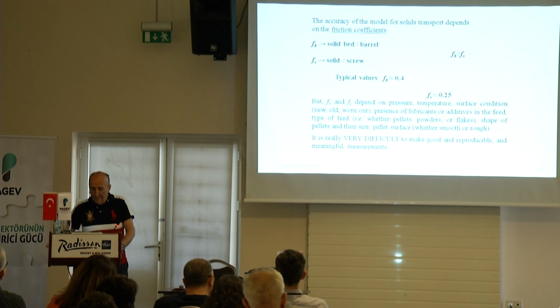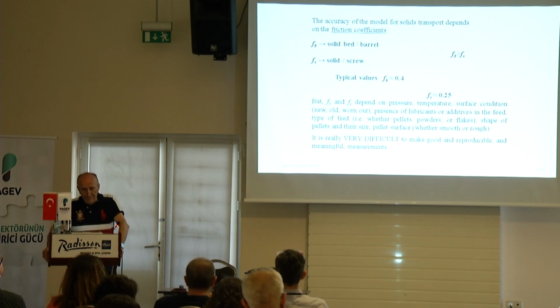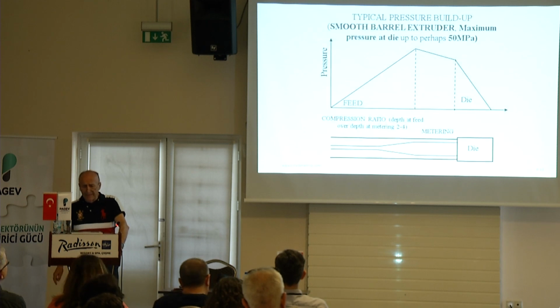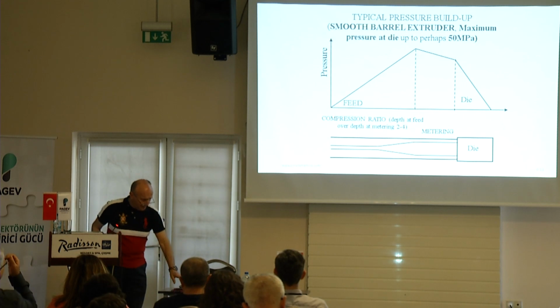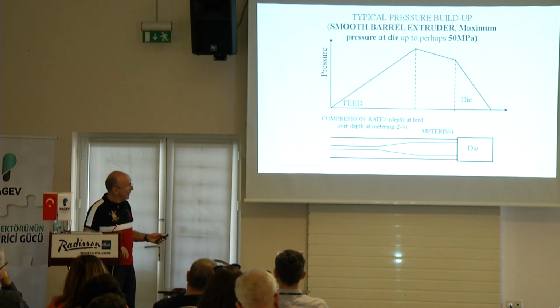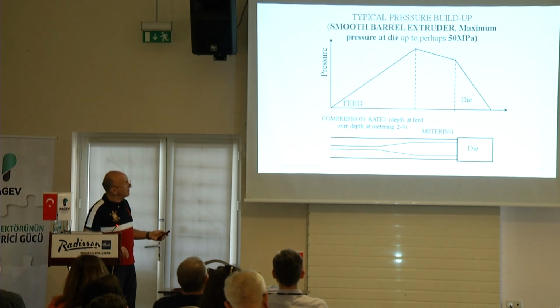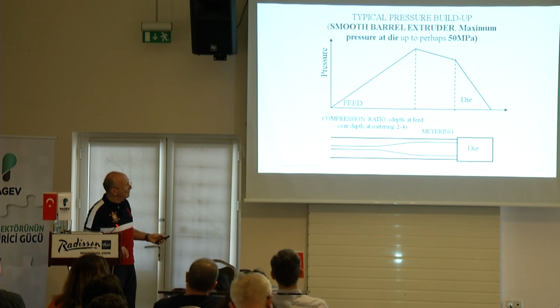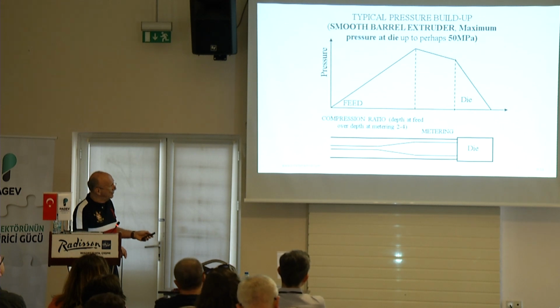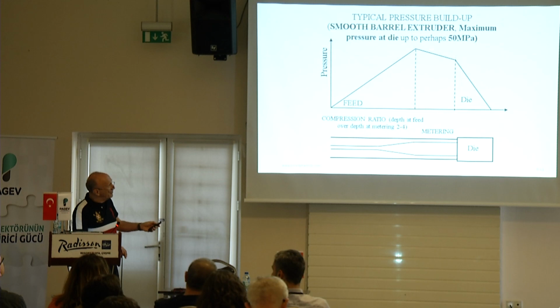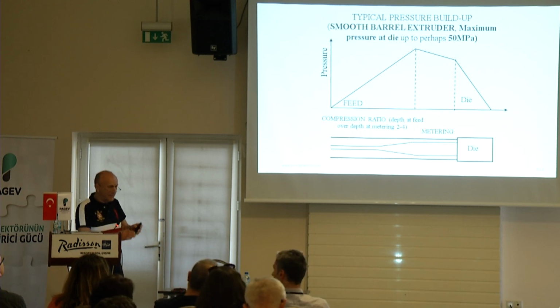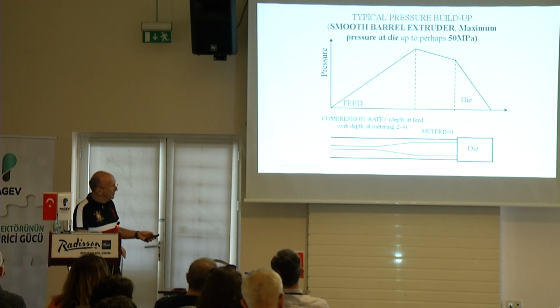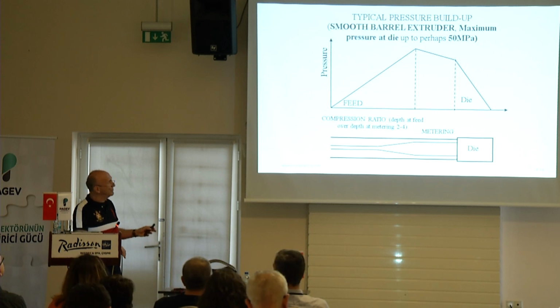So I say the same thing again, solid bed, barrel, it would have to have 0.4 and the screw 0.25. And typically the pressure variation along the screw will be of that shape. This screw in that particular case is going to be a gradual build-up. Here we are compressing. This is the typical design of a screw. It's a straight portion, we do the feeding right here. Then it's compression, which gives some pressure rise because you're compressing it. Then you have a straight portion, which is the metering section. And then, of course, you have a large pressure drop in the die. So this is what you get.